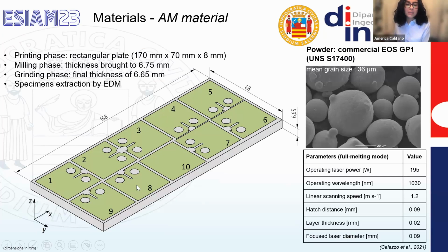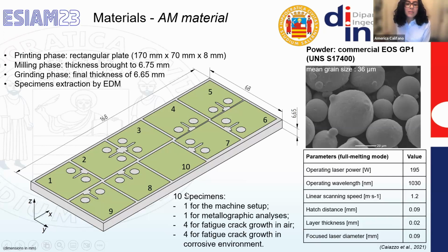Here you can see a schematization of the plate, from which 10 specimens were extracted by means of the electric discharge machining method. In particular, one specimen was used for the experimental machine setup. One specimen was used for carrying out metallographic analysis, and the remaining 8 will be used for carrying out experiments about crack growth, both in air and in corrosive environment. In this contribution, I will show the results for specimens number 2 and number 5 that are, as you can see, characterized by notches that are along 2 different directions.